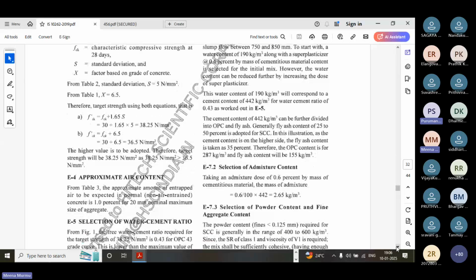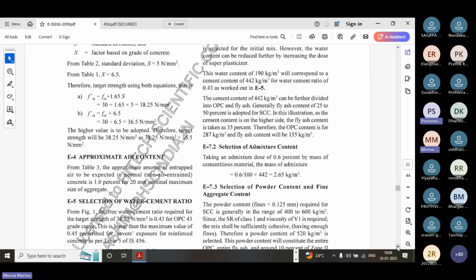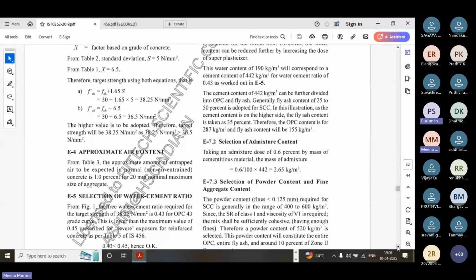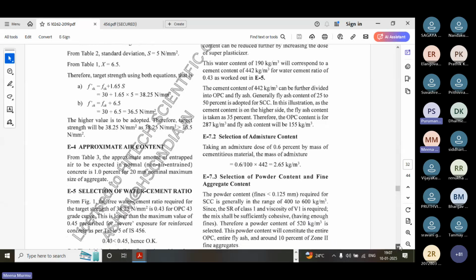And the content of 442 kg per meter cube can be further divided into OPC and fly ash. Generally the fly ash content is 25 to 50 in SCC, self-compacting concrete. But whenever you go for high strength concrete, if you add fly ash, then your strength will be reduced. And suppose you go for high strength, then we can add VMA with silica fume also. So here this is your fly ash and cement content. Then selection of admixture is as per the cementitious material we can take.